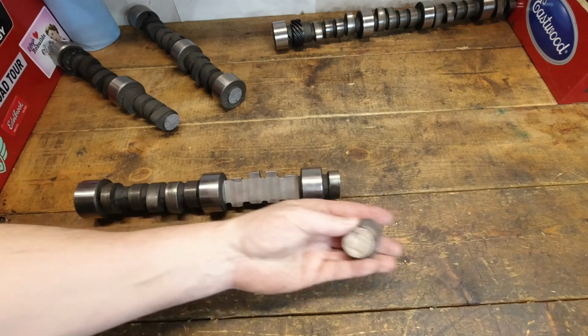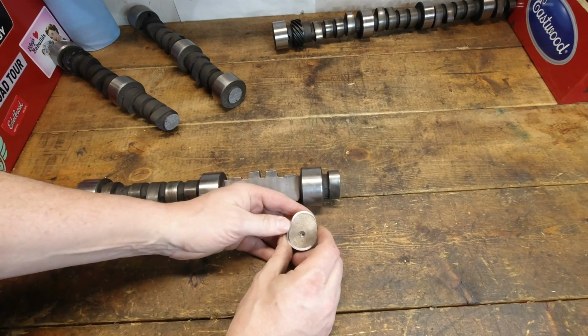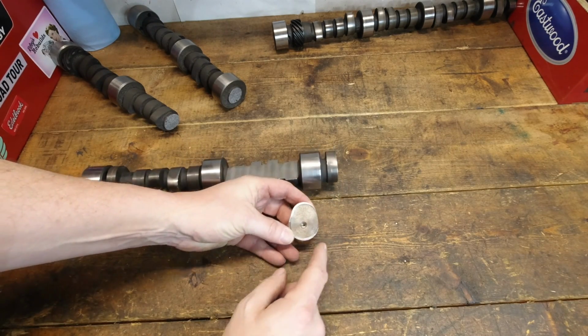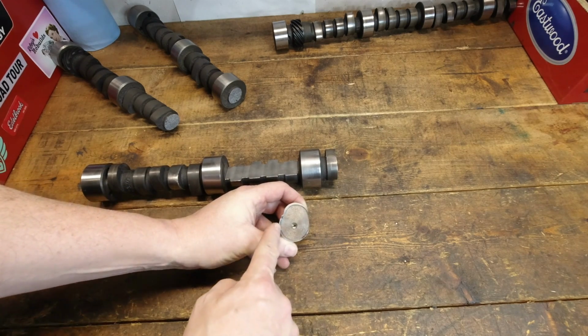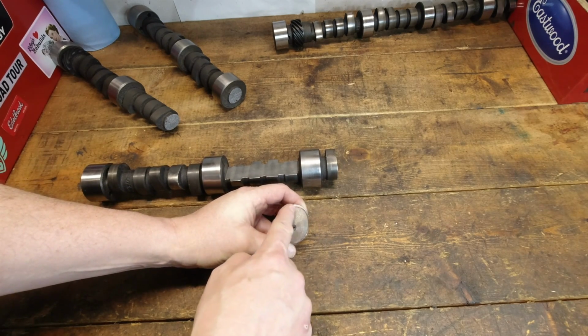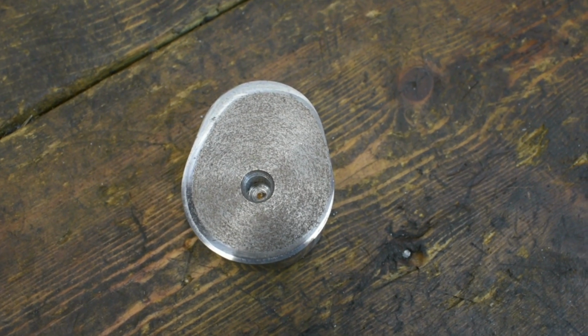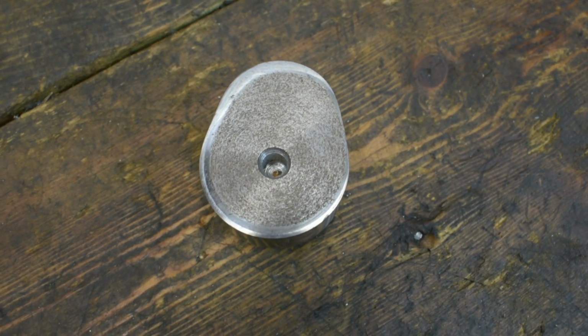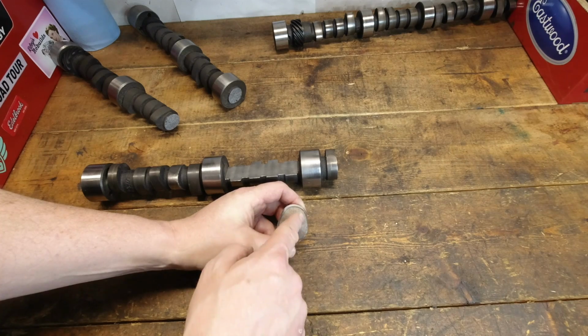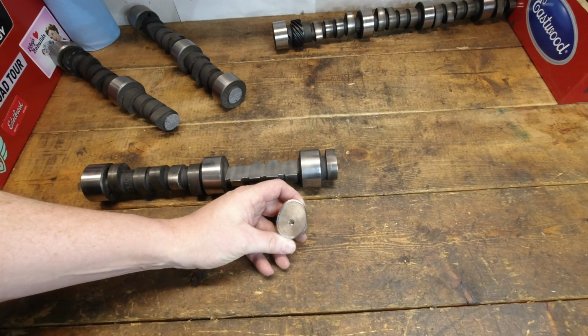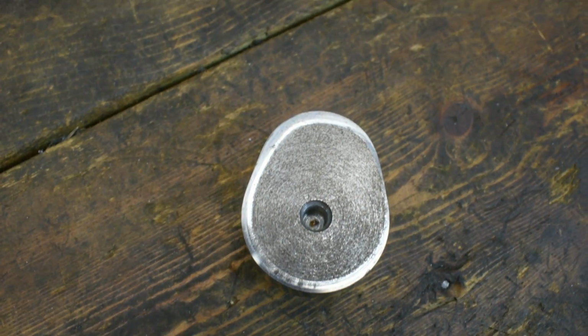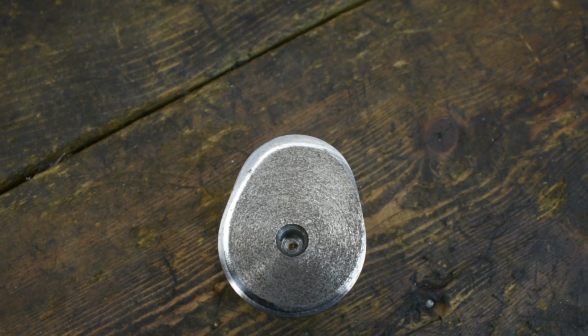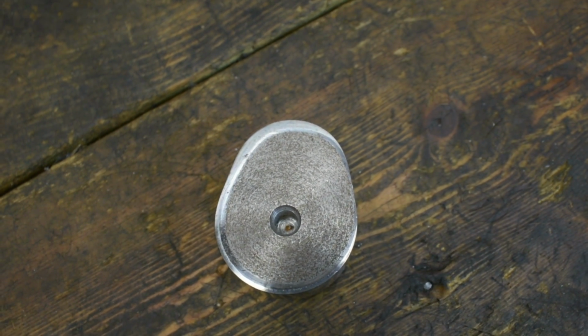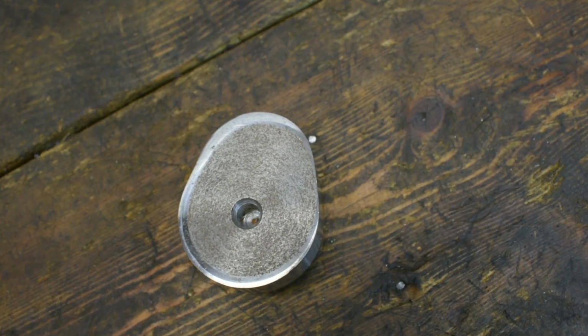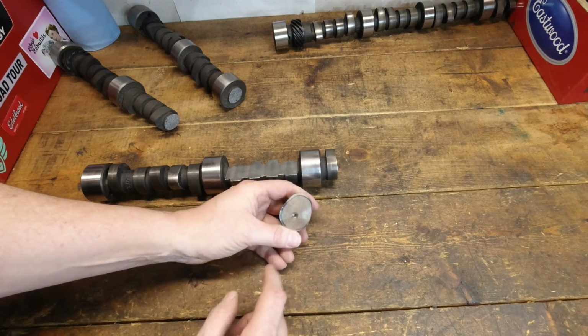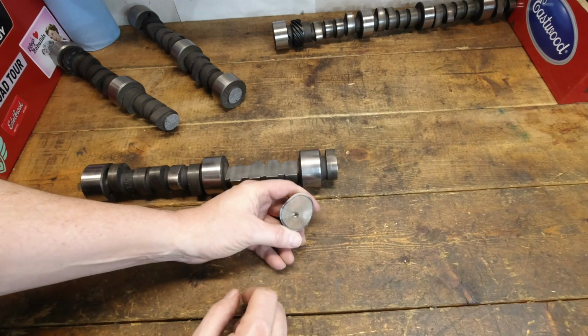If you look at this one here, it's a different material, obviously, but here's a good example of one where you've got good heat treating. This is a billet camshaft core. You've got good heat treating around the edges, but you got this one edge over here that is dangerously close to being into the softer material and could cause an issue. Now that's a hydraulic roller or solid roller lifter lobe. You can tell by the profile of it.